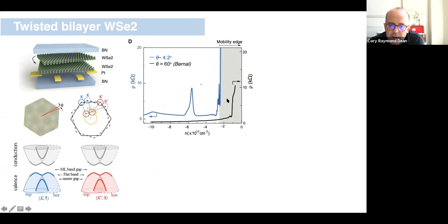What we see is that, as we try to inject carriers into the system, because this is the valence band, we're going to label the densities as negative values. On the right-hand side of this plot, we're just in the intrinsic gap of WSe2. And as we dope, or increase the hole density, to the left, the first thing we see in this blue curve, this is a device with twist angle 4.2 degrees, is a resistance peak in the response at some point, and then we see a second resistance peak in the response.